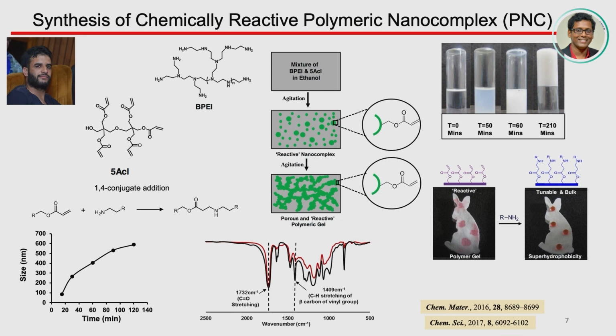So this carbonyl acts as an internal reference, and if you normalize the spectra with this particular IR position, then the depletion of the signature at 1410 precisely tells that these residual acrylate groups are reactive in nature, and you can react them with a small molecule to modulate the surface chemistry around this nanocomplex also.